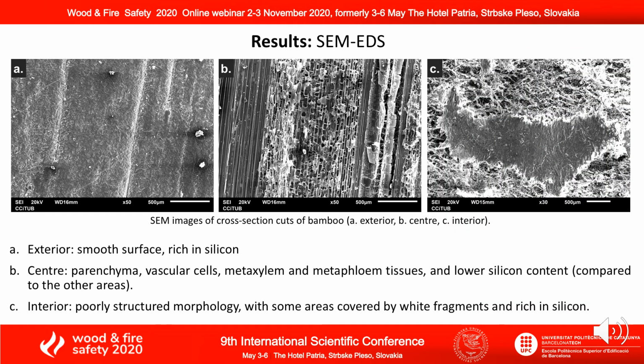In the scanning electron microscopy, we can observe that the external part of the bamboo shows a smooth surface rich in silicon. The central part has an ordered structure with parenchyma, vascular cells, metaxylem and metaphloem tissues, and a lower silicon content. And the internal part is poorly structured, with some areas covered by white fragments and rich in silicon.